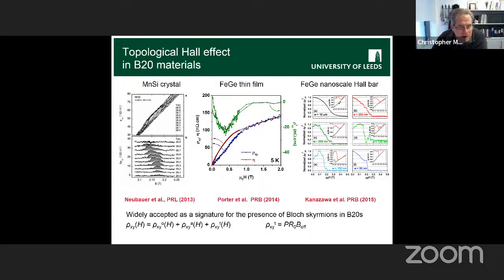So you measure a Hall signal, and that contains ordinary and anomalous, as well as this topological part. We can write down the topological part as coming from this effective field that's coming from the Berry phases. We can convert that into a Hall resistivity with the ordinary Hall coefficient and a spin polarization that goes in front. But to pick this out from the measured signal, you have to get rid of these two other components.